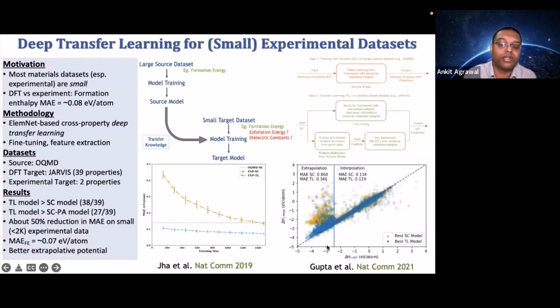But in the extrapolative regime here, the scratch model just fails, because it has not seen anything like this before. So there's a big error. The transfer learning model, although there is a bigger error compared to the interpolation regime, is still somewhat close to the diagonal. So these transfer learning models have much better extrapolative potential, which is a big deal in machine learning, and especially for materials applications, where the goal is to discover new materials which have not been seen. So by definition, you need the model to do extrapolation well.